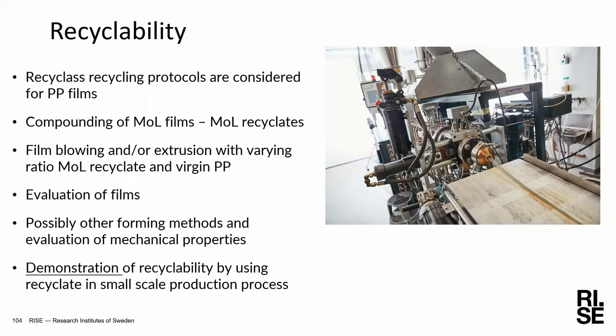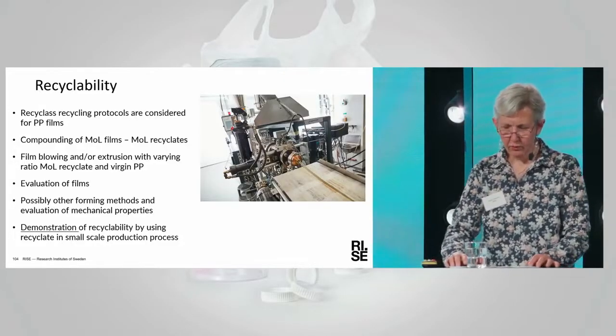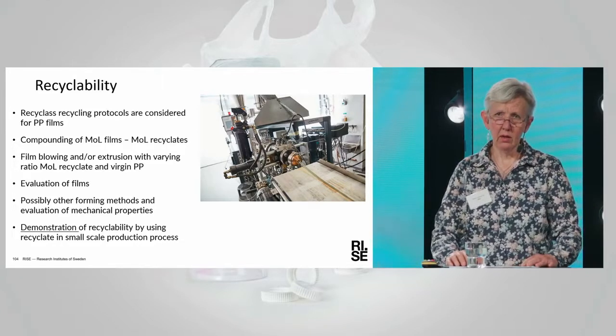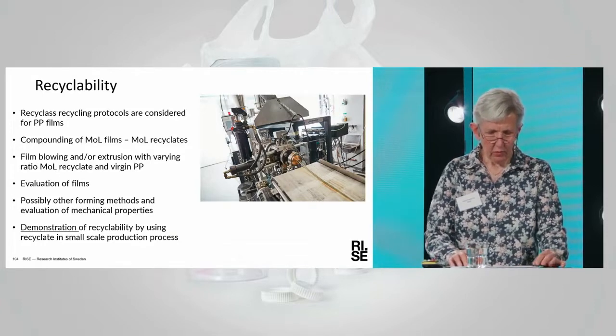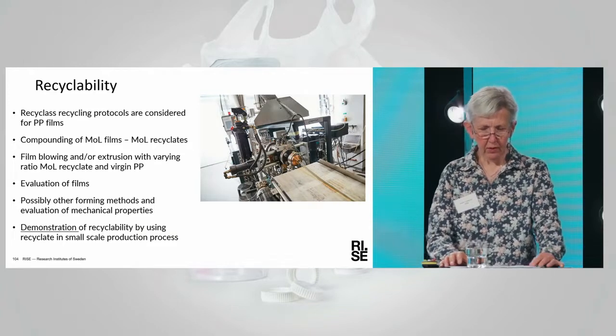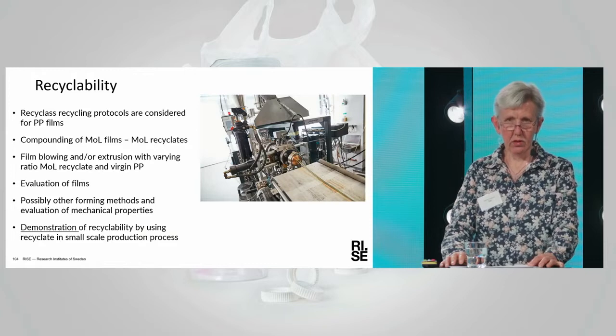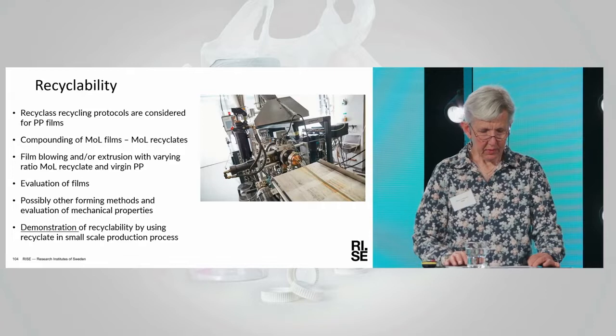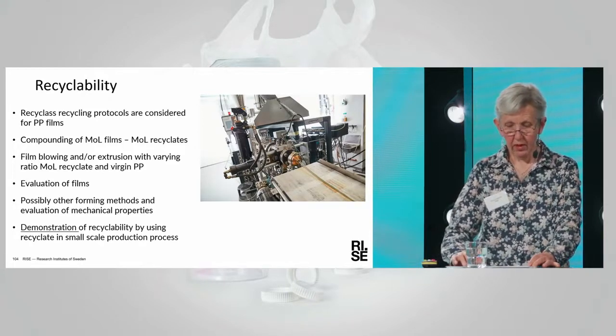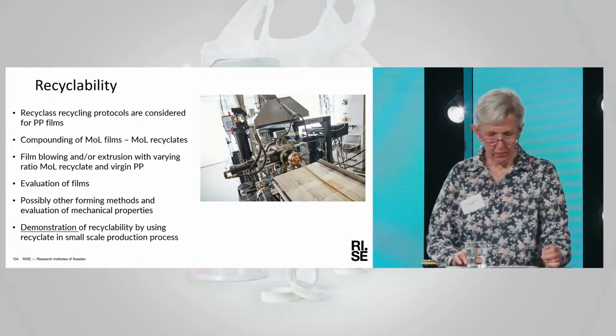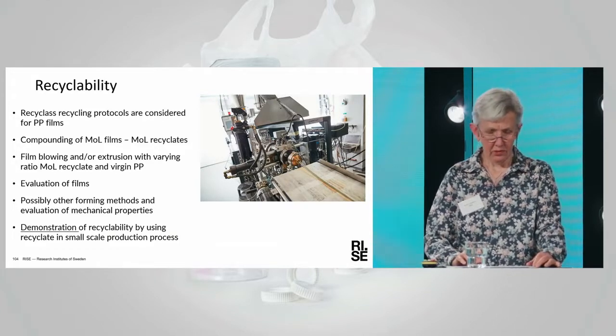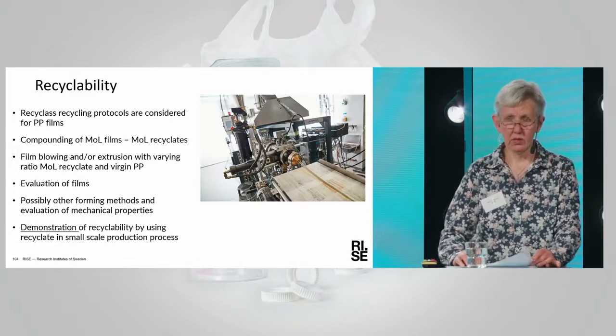And in the work package about recyclability, we have been looking at and have considered the Recyclass recycling protocols. They are really interesting and well built up. So we will do compounding of monolaminate films and in that way obtain monolaminate recyclate. We will do film forming, mainly blowing, with varying the ratio of the recyclate and the virgin material. Perform the evaluation of films, and when it comes to PP, possibly also other forming methods and evaluation of the mechanical properties. And then we will have the demonstration of the recyclability by using the recyclate in a small production process.